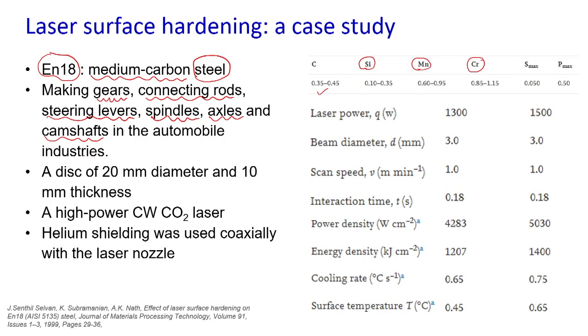For this experimental study we are considering a disc of diameter 20 mm and thickness 10 mm. To carry out the hardening operation we can use high power lasers, either a solid state Nd:YAG laser or a CO2 laser. Here a CO2 laser is used in CW (continuous wave) mode, not in pulse mode, for the surface hardening process.